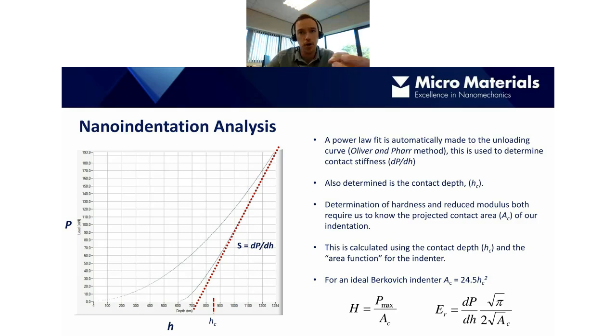Once we've got hc, we can then get the contact area, Ac, which is what we're really after. For an ideal, theoretically perfect Berkovich indenter, the contact area is equal to 24.5 multiplied by the contact depth squared. From that, we can plug it into our equations down here. The indentation hardness is defined as the maximum load divided by the contact area, and the reduced modulus is equal to this term here, which is the stiffness multiplied by this factor, which includes the contact area.